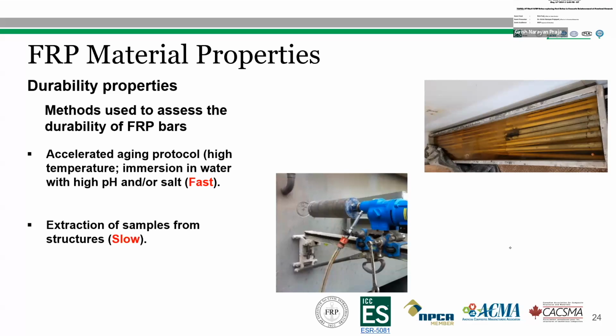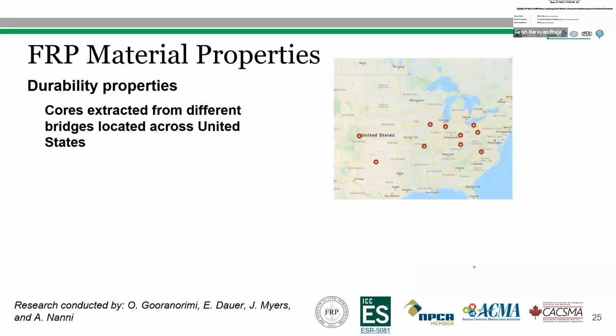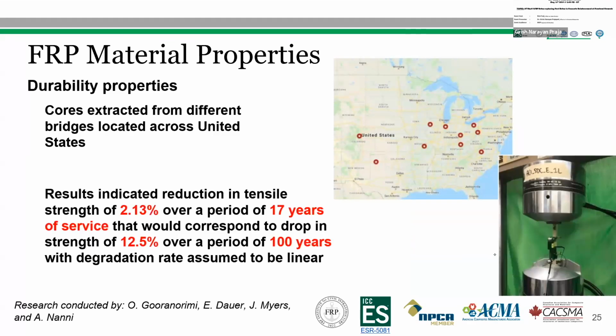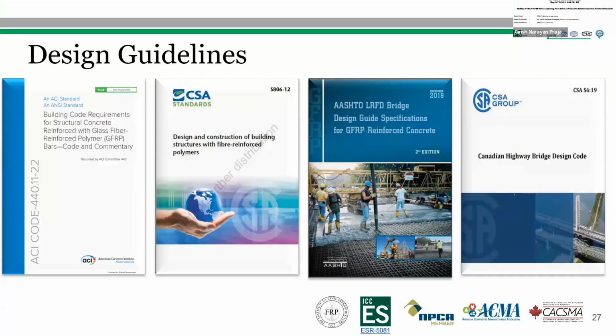The second process is the extraction of samples from real structures. This is a slow process, and the test is conducted after 15 years of structure service. The durability of GFRP reinforcement in concrete was assessed by excavating cores from different bridges located across the United States. The results from the study indicated a reduction in tensile strength of 2.13% over a period of 17 years. That would correspond to a drop in strength of 12.5% over a period of 100 years, with the degradation rate assumed to be linear. So in the next section, we'll talk about the design guidelines.